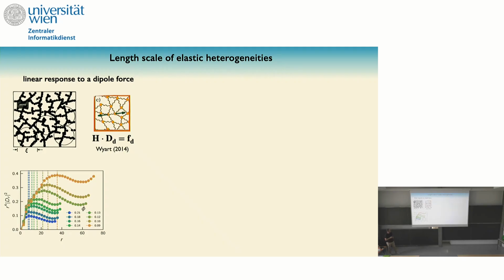And what you can do is take your sparse gel, go in different places, apply these dipole forces, measure the displacement field, and then plot it times the expectation that you get from linear elasticity, right? So here is what you get from linear elasticity. But you see that below you have a length scale where you have a deviation from linear elasticity. And this deviation tells you that you don't recover linear elasticity any more and you are probing the heterogeneities in your system. And this is the way we define this length scale. It's a length scale that is a measure of the mechanical heterogeneities, in some sense, of your system.